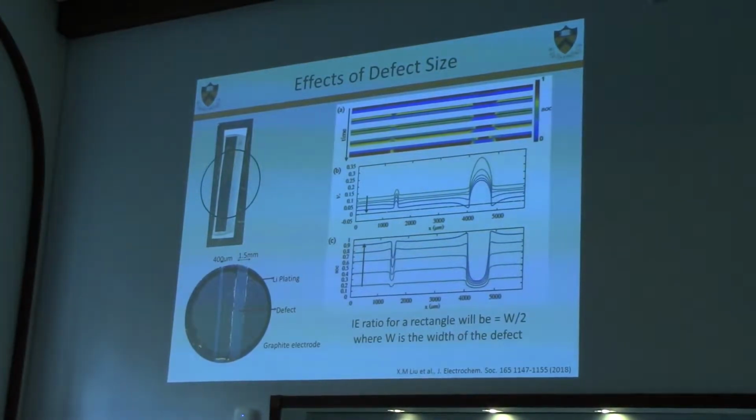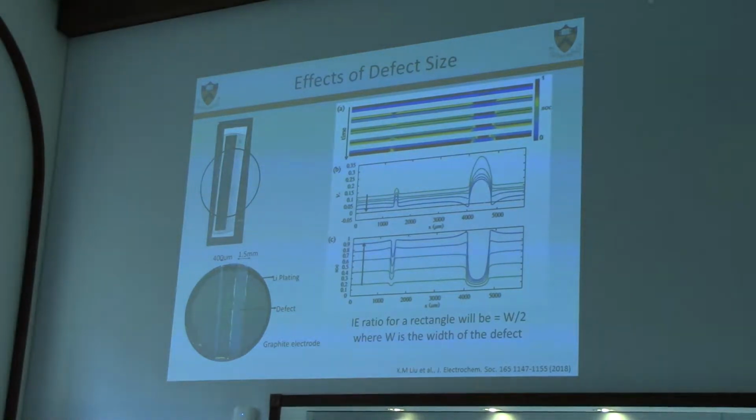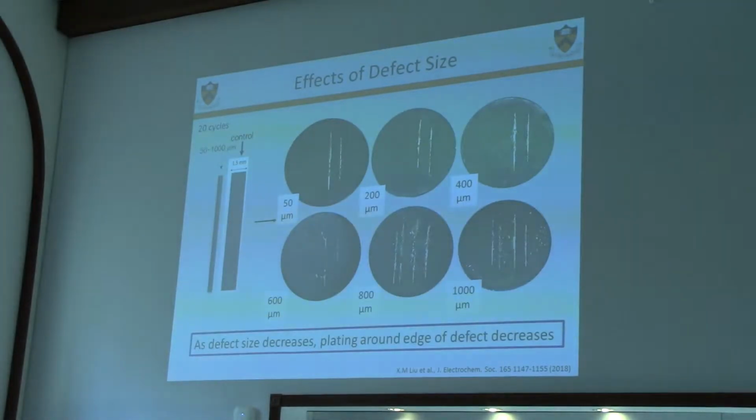But let's start getting to a critical size here, right? So it seems to me that when I looked at the triangle, I found that at the vertex it didn't plate, on the side it did plate, which means there has to be some size scale at which plating doesn't occur, because this defect is small enough that the ions can move around, can avoid the defect, and can happily intercalate and deintercalate. And so we can ask, what is that going to depend on? And we know it's going to depend on the transport and the relative properties of the material.